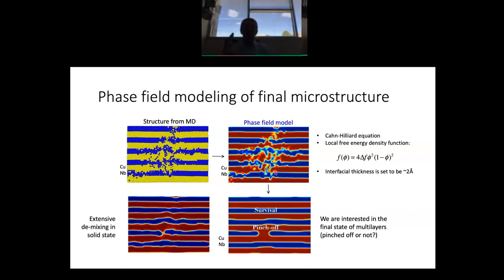We use the Cahn-Hilliard equation to model how this initial state evolves, and that simulation is shown here on the bottom left. So what it shows you is that because of the phase separating nature of the copper and the niobium, these two materials actually demix substantially, in the solid phase over a long period of time. So a lot of this damage that was created by the thermal spike is actually recovered, right? The fact that you have a lot of mixing doesn't mean that all of these layers broke down. However, once in a while, occasionally, like in the case of this layer right here, we do see a pinch-off event. So this, for example, is an example of a pinch-off event. This layer up here survived, but this layer pinched off. So clearly, thermal spikes can actually initiate this morphological instability, causing layers to pinch off.